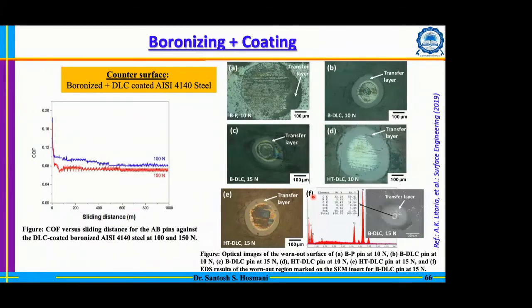So what is the reason? Basically, as you keep on applying the load, there is a formation of a transfer layer. It is a graphitized layer, and that graphitized layer helps in reducing the wear loss as well as reducing the coefficient of friction. That is the basic mechanism which is happening because of the DLC coating.